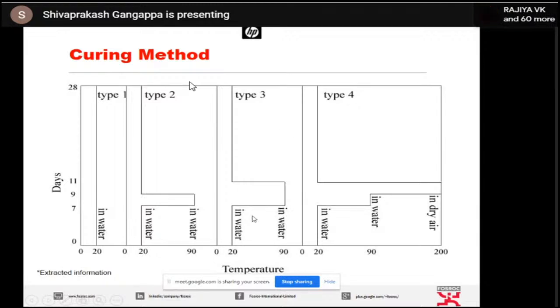Third set is where initially the temperature is 20 degrees. What I'm talking about is the curing water temperature. If you take any ACT, accelerated curing test chamber, it has control on the temperature of the water placed for curing. So you can maintain the temperature of the curing tanks, so that the water has a temperature of 20 degrees for 7 days. Then after 7 to 9 days, 60 degrees, 90 degrees, then again it comes back to 20 degrees, and it continues for 28 days.